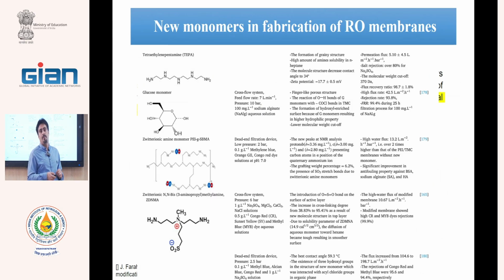In this case, we have polyester instead of polyamide, and polyester have good chlorine resistance, but usually have lower flux. In most cases, want to increase the flux with increase of the hydrophilicity. For example, when we have this Zwitter ionic compound, the amine reacts, and these groups increase the hydrophilicity, and most of Zwitter ions have antibacterial properties.